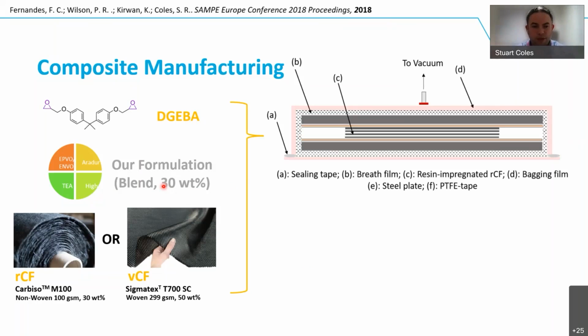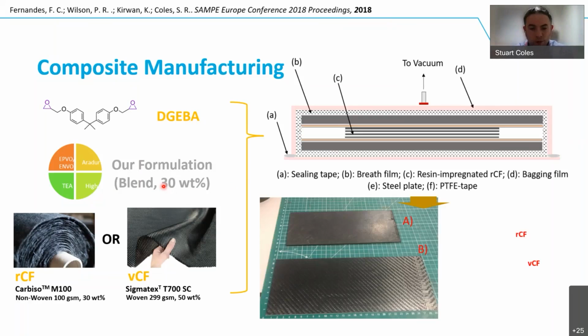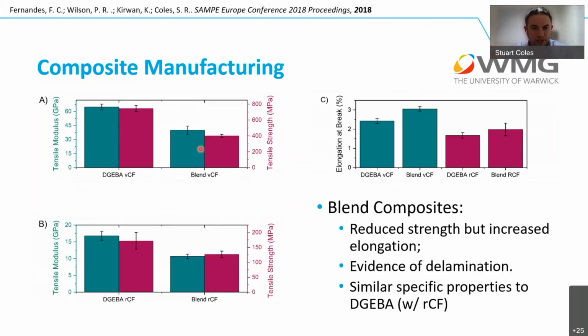So we made them with traditional composite manufacturing with the two different fiber types. Even though we had different fiber diameters and fiber weights, we tried to keep them fairly consistent overall in terms of the amount of material in there. And we created these carbon fiber composites, which had 30% bio-based resin in them. And we found, again, that the tensile modulus of the bio-based was lower, and as can be seen here with the virgin carbon fiber, tensile strength, everything with the recycled carbon fiber was lower again as well. So we know that the blend performed lower. We actually got a more ductile sample as well, as would be expected. With virgin carbon, the blended materials gave us the mechanical properties exactly as we would expect in this particular area.